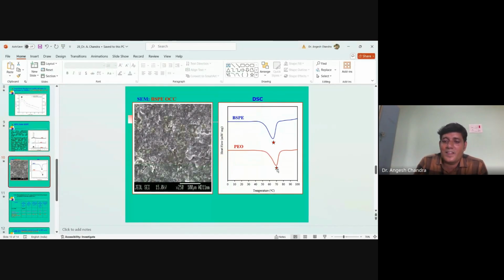This is the melting point temperature of pure PEO, approximately 70 degrees Celsius. And in this blended solid polymer electrolyte, the melting point temperature is shifted towards the lower side. It means the flexibility also increases, so the conductivity also increases. And this is great evidence for the conductivity enhancement of our blended solid polymer electrolytes.